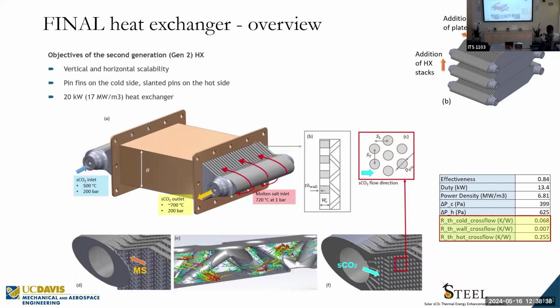So if you look in this table, the little boxed region here, we have the thermal resistance. So RTH stands for thermal resistance. So basically, how difficult it is to transfer heat in that particular section. And so RTH on the cold side is about 0.07 Kelvin per watt. But if you look at the thermal resistance on the hot side, it's more than 3 times that value. So really the bottleneck to heat transfer is on the hot side.